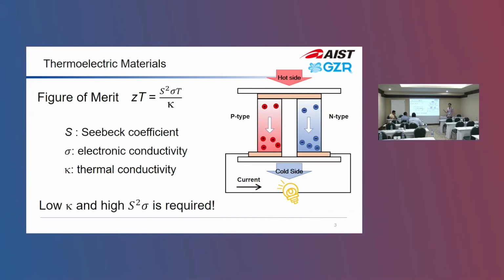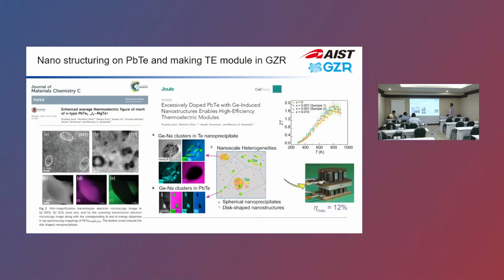As he explained, ZT is a very popular index for thermoelectrics, and the difficult point is achieving low thermal conductivity with a very high power factor, or high electrical conductivity. That's a simple idea. Our group is working on nano inclusions for high performance materials like lead telluride or bismuth telluride as well. They can reach a ZT of up to around 2.